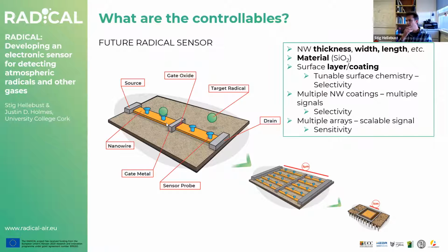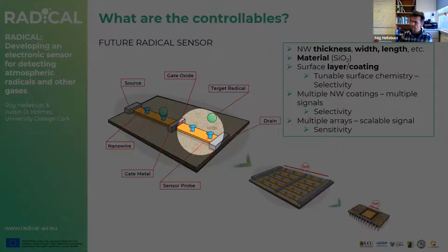Now, to pick up where Justin left off, I'll take you through some of our preliminary results and a little bit about our experimental procedures and design and how we're going with that. Looking at this diagram of the nanowire, the signals that we want to measure are influenced by several things. The sensing part of it is the chemical interaction between the nanowire surface and the target species in the gas phase. But the signal that we measure is also influenced by the physical parameters of the wire: the dimensions of the wire, the thickness, the length, the material that it's made of, and the oxide layer that Justin explained about on the surface. So for the calibration, we have to study not just the sensing part of the signal, but also all the other interferences.